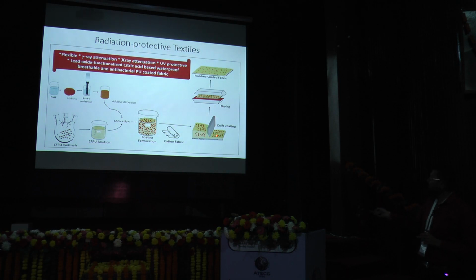We have the coated layer with a filler, and then we tested all properties along with X-ray protection and gamma ray protection. And we found encouraging results. It showed excellent resistance against X-rays. X-rays are not allowed to pass, at least in an excellent range. And gamma rays, we got a good result compared to literature.